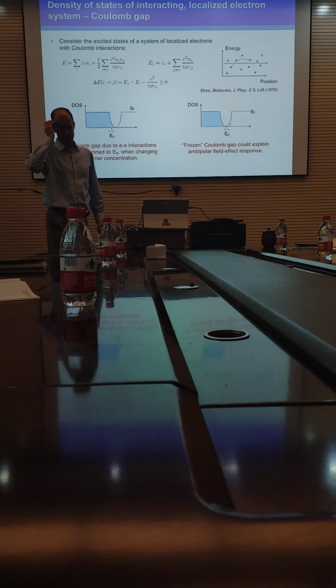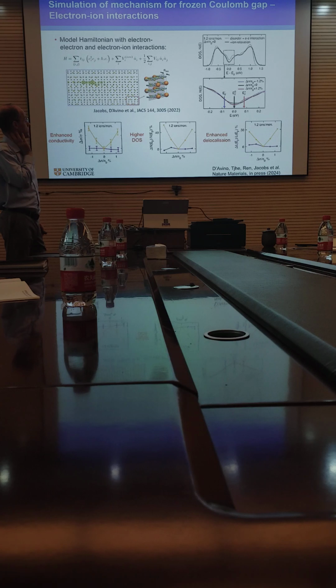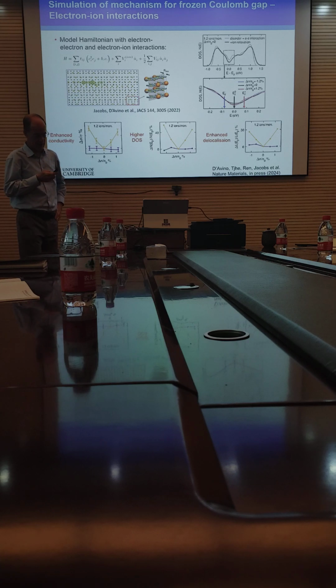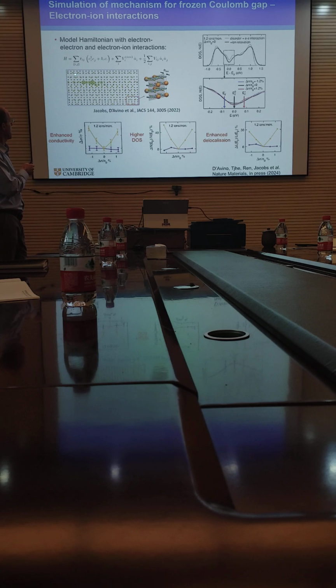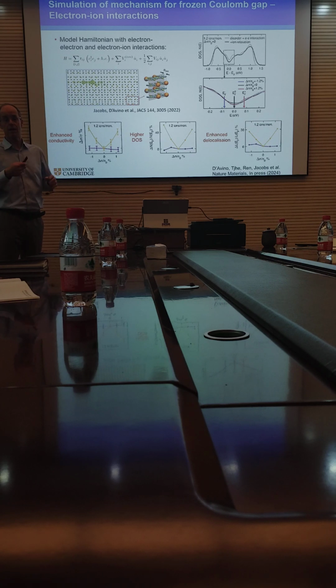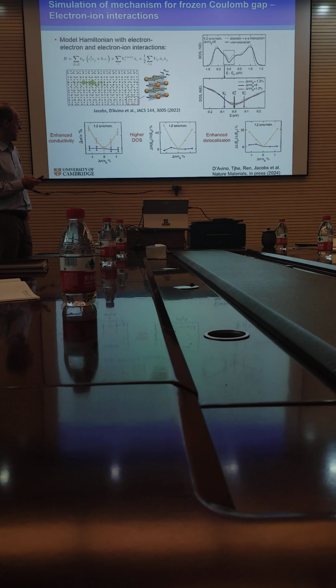And so we worked with theoreticians, with Gabriele D'Avino in Grenoble, who is in Simone Fratini's group, and they developed this model Hamiltonian for a system like this. I've shown the picture before, so you have sites. These black dots are sites. This direction here from left to right is the polymer chain axis. The direction from bottom to top is the pi-pi stacking axis. And then you introduce dopant counterions. These orange blobs are the dopant counterions. And then you calculate the electron wave function, and you can calculate the conductivity. So it's quite a realistic model of a polymer system. It's carefully parameterized with DFT calculations to make sure that the disorder is taken into account in the correct way.